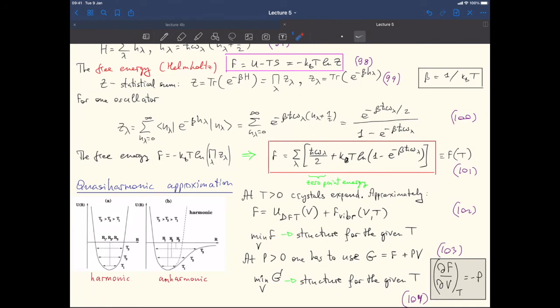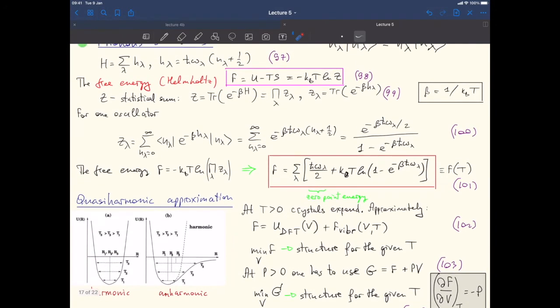So we take a particular lattice constant, and for that lattice constant, we relax atomic positions. This needs to be done only if there is more than one atom in the unit cell, of course. So then we determine the DFT energy of that structure.